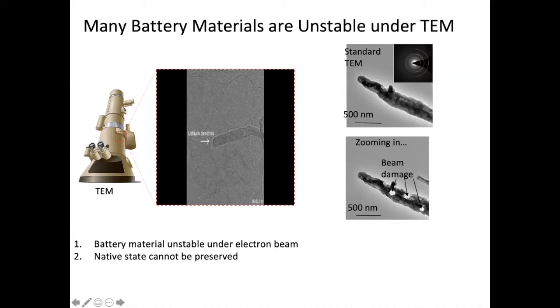So this is on the material design. We know interface is very important, right? To understand the interface, we really need a new tool to guide us in the design of the interface. I want to share with you, if you look at a fragile beam-sensitive material such as lithium metal under TEM at room temperature, this lithium metal is going crazy. You just start to zoom in, and you're going to destroy this lithium metal dendrite right away. There's no way you can do imaging and understand these materials, understand this interface.